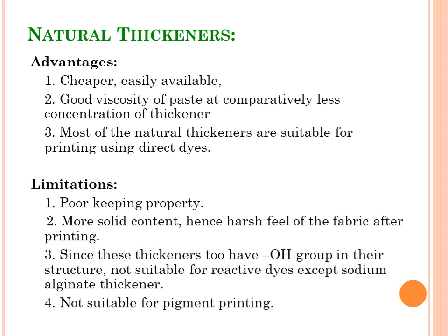Then foam generation also occurs because of bacterial attack. Day by day, we find that the viscosity is decreasing and at last the paste becomes watery. So it is no longer of any use. This poor keeping property is the biggest limitation of natural thickeners because these are food materials that get easily affected by bacteria.